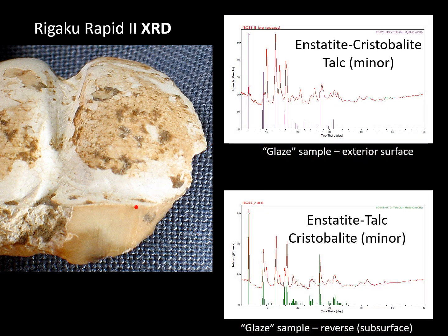The surface was found to be enstatite and cristobalite with a minor amount of talc. Directly beneath that, it was enstatite and talc with a minor amount of cristobalite.